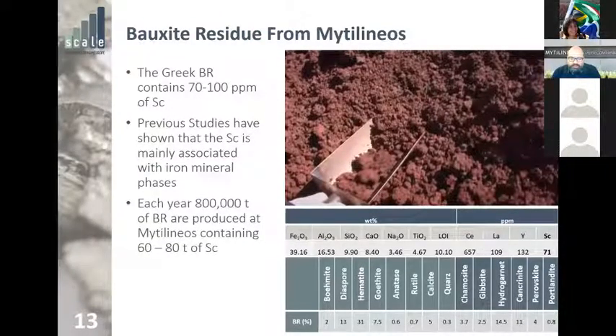Also you can see the mineralogical analysis of the phases of the bauxite residue. The left side shows the phases that are there from the initial bauxite ore, leftover non-leached phases. So mainly some leftover alumina phases, followed by iron phases, titanium phases, calcites and quartz. And then you have the new phases formed during the Bayer process, which are secondary precipitations like hydrogarnets, cancrinites, perovskites, and so on. And gibbsite is obviously alumina that precipitates out of the solution before we have a chance to separate it. Each year we produce at our site close to 800,000 tons of bauxite residue.